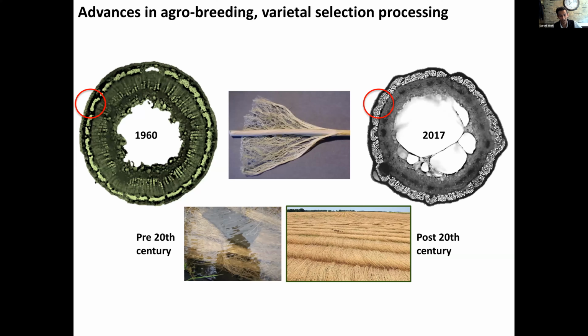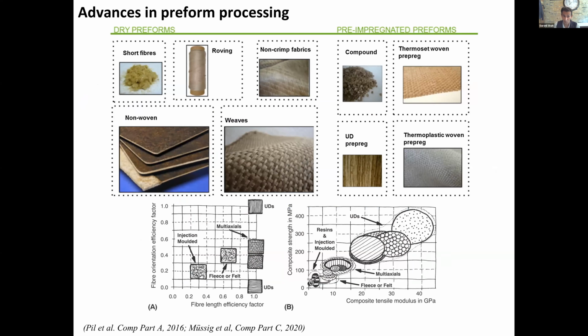There have been lots of advances over the past centuries, particularly in agrobreeding. So this is a hemp stalk, and you can quite clearly see that since the 1960s, we have worked quite a lot to increase the yield of plant fibers, but also changes in approaches to, for example, retting. Rather than pond retting, we now use dew retting or field retting because it's more environmentally friendly rather than polluting our waterbeds. There have also been advances in preform processing.